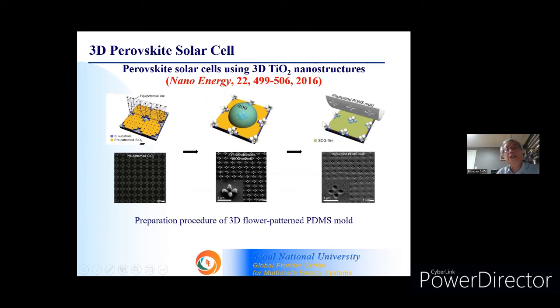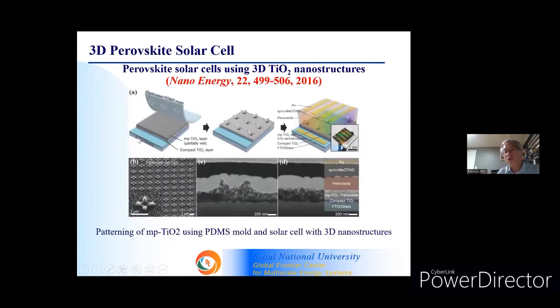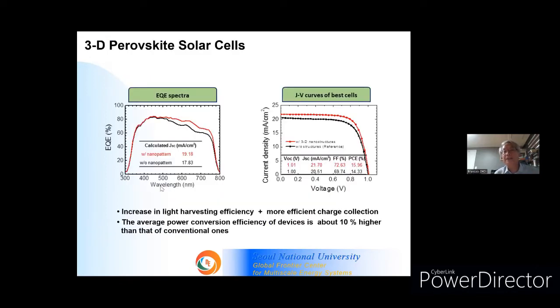So first we make this flower structure, and then we can replicate a PDMS mold. This is the PDMS mold, and using this mold we can make patterns of mesoporous TiO2 layer like this. We want to enhance light scattering using this kind of three-dimensional pattern.